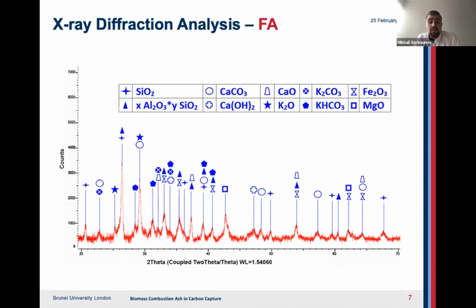Similarly, K2O is also a noteworthy compound. Again, in the presence of moisture, the reaction with CO2 leads to bicarbonate formation. Therefore, one molecule of potassium oxide supplies two atoms of K, each of which could attach to a bicarbonate ion, thereby contributing more to the capture process on the scale of per molecule of substrate than an oxide or a hydroxide of a bivalent metal.